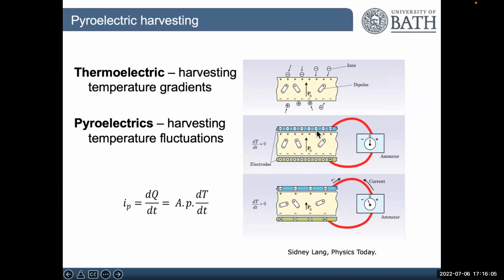So again, if we imagine our poled particle, which can be a ferroelectric material, a device, or even a particle within a solution, if we heat it up, then the polarization will fall. And so some of these screening charges on the surface of the material are free to take part in a current flow or to take part in an electrochemical reaction. And likewise, as we cool the material and the polarization returns or increases, then current will flow in the opposite direction to rebalance that charge. So again, it's very much the same effect. So all the ferroelectrics are both piezoelectric and pyroelectric.